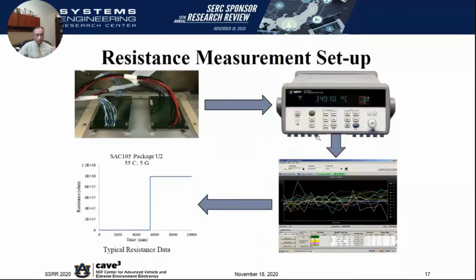So simultaneously, what we have also done is we have subjected the board assemblies to a sustained period of thermal storage, and that's why you see a slightly darker green color because of extended thermal storage. These assemblies have then been mounted on an electrodynamic shaker. So that's the inside of the chamber. So there's a thermal chamber around the shaker that allows us to run the shaker at a variety of temperatures up to 300 degrees centigrade, although the data that I'll show you today is for up to 155 degrees centigrade.